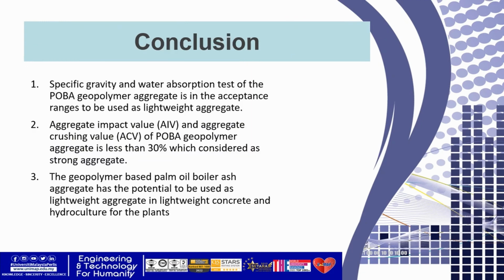As a conclusion, the specific gravity and water absorption tests show that the POBA geopolymer aggregate is in a suitable range to be used as lightweight aggregate. The aggregate impact value and also aggregate crushing value for POBA geopolymer aggregate are less than 30%, which is considered a strong aggregate. Geopolymer-based palm oil boiler ash POBA aggregate has the potential to be used as lightweight aggregate for lightweight concrete and also for hydroculture for plants.